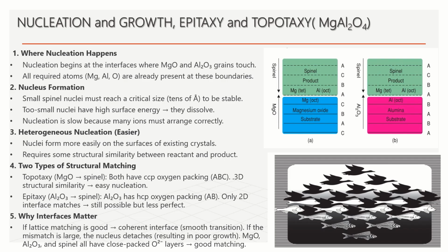octahedral sites. Because the oxygen framework is almost the same, forming the first layer of spinel on top of MgO is very easy. This is a three-dimensional structural match and we call this type of growth topotaxy.